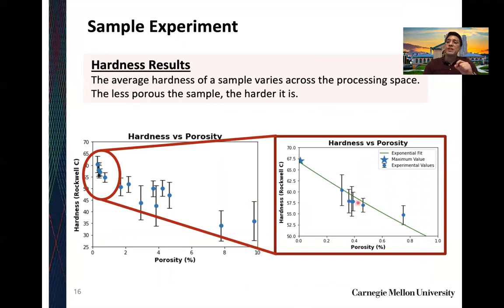are approaching the maximum value predicted by the manufacturer of our powder, which is about 67.5 Rockwell C. And if we fit this trend here with an exponential fit, we see a very decent fit. All our parts are well within the predicted exponential fit. So if we can further optimize our selective laser melting process of this material system, we can further decrease the porosity and get closer and closer to that maximum theoretical value.